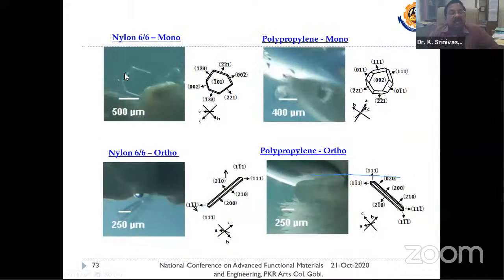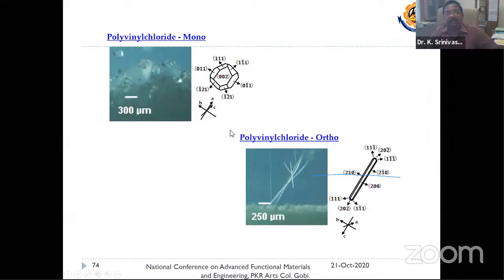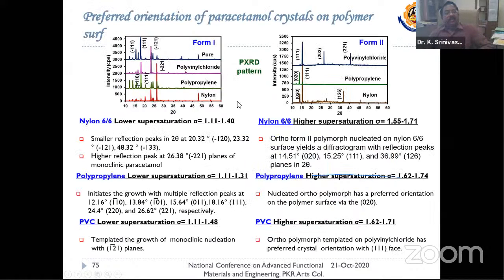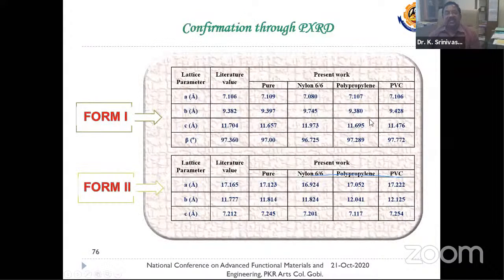And these are some of the nucleated close-up monoclinic crystals. And these are some of the needles, orthorhombic polymorph from nylon and PP. Similarly, the PVC, monoclinic as well as orthorhombic nature, carefully captured under the microscope. So the ultimate confirmation is once again the powder X-ray diffraction for the mono form nucleated with these polymer templates, and form 2 orthorhombic nucleated by these three different polymers. So these are all the structural parameters for form 1 and form 2 compared with the literature values. Okay, very much confirmed here.